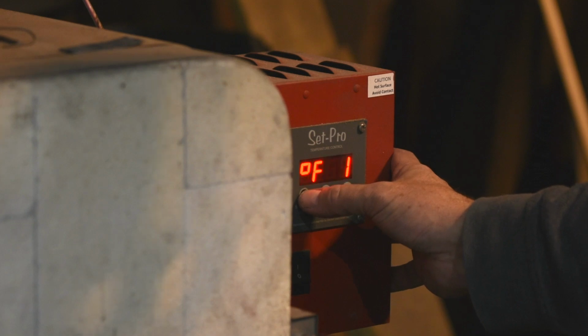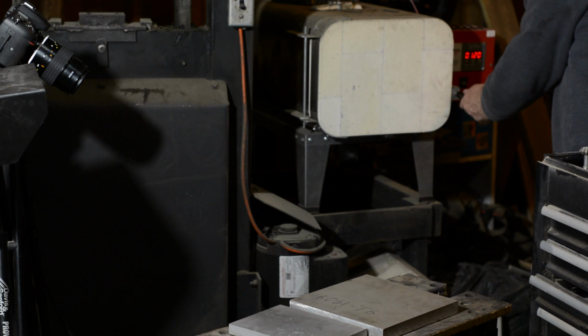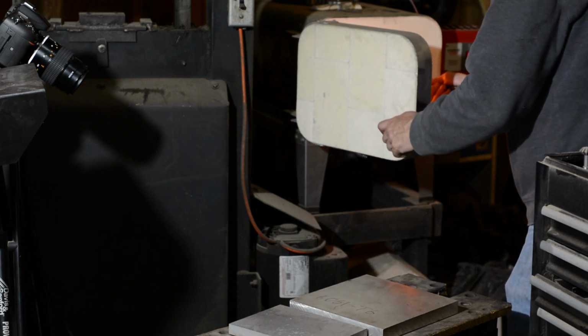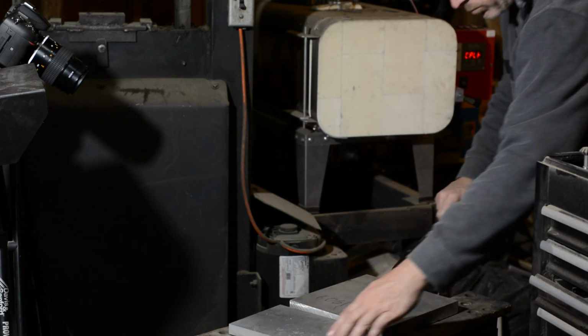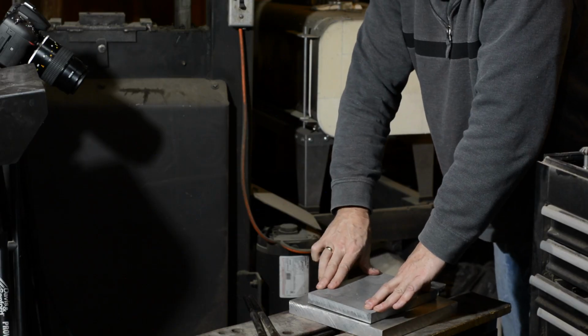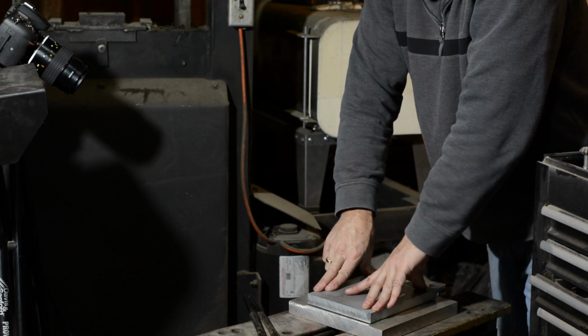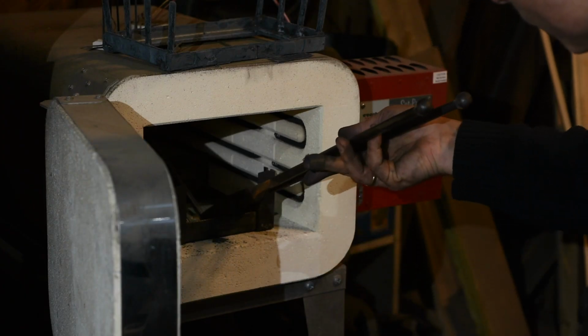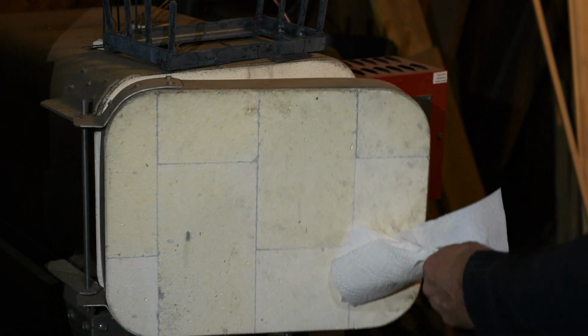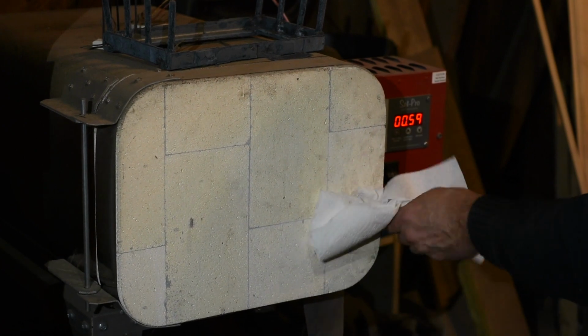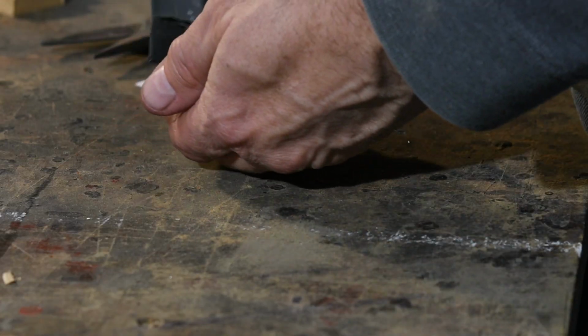After soaking, the blade and the little packet it's in is taken out and pressed between two aluminum plates. You can also quench in still air and it'll work just fine. The plate quench approach lessens the likelihood of warping, however. The steel is then given 2 tempering cycles of 2 hours each at 400 degrees Fahrenheit. And here's the blade after heat treat.